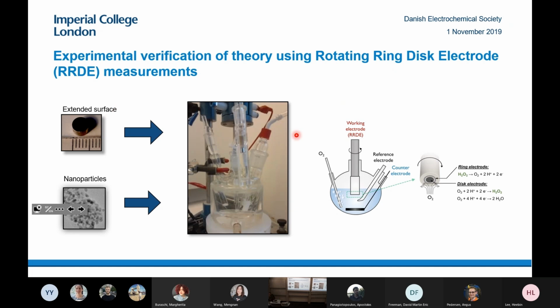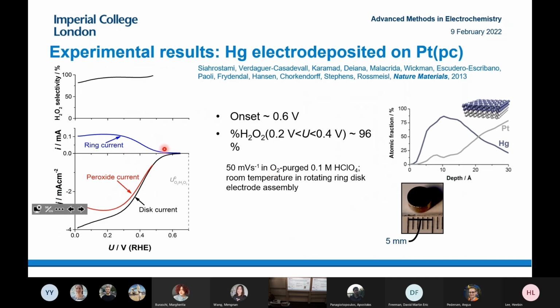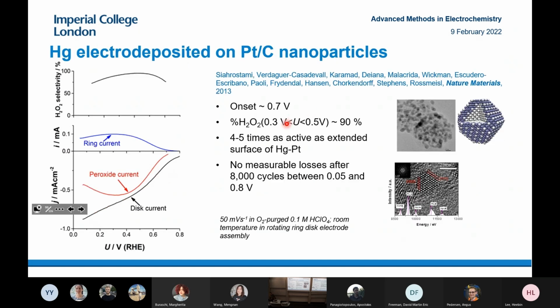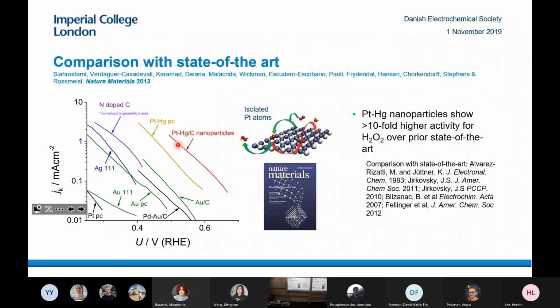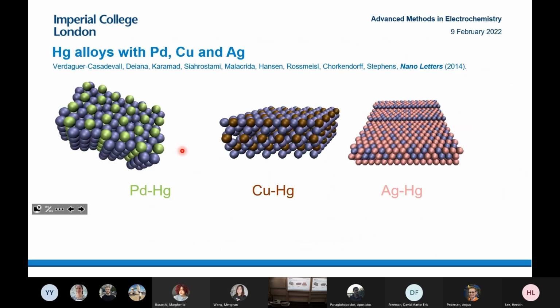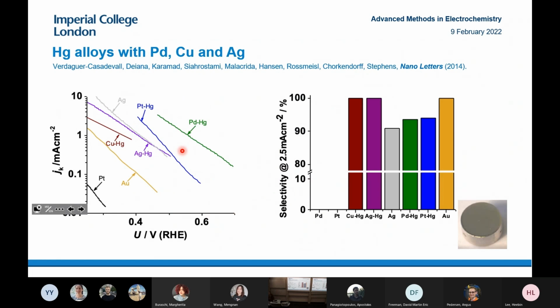Anyway, we took a platinum single crystal, and we also took nanoparticles, deposited mercury onto them and tested for oxygen reduction. Using what's called rotating ring disk electrode experiments, we can measure how much hydrogen peroxide is produced. We could see that the amount of hydrogen peroxide being produced tracked the overall current for the reaction, and it was the same for nanoparticles as well. They were really active, much more active than what people reported previously. We also looked at a number of different alloys, like palladium mercury, copper mercury, gold and silver mercury. We found palladium mercury is even more active than platinum mercury.